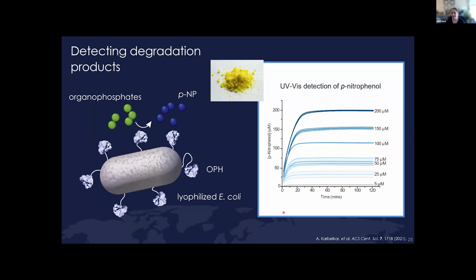The problem here, if anybody here remembers their analytical chemistry classes from undergrad, is we see very large errors at both 50 micromolar and 25 micromolar concentrations. And so when we back calculate the limit of detection from this amount of error, we actually get concentrations as high as 50 micromolar for our consistent limit of detection. And 50 micromolar is higher than the lethal dose of this pesticide. And I would argue that a sensor that only detects at above the lethal dose is not an especially useful sensor.